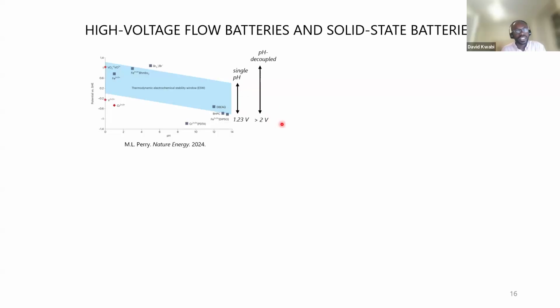But the other advantage we've realized that these membranes carry is that because they are perfectly selective, in this case for sodium ions going from the negative to the positive electrolyte, we can have two different pH environments on either side of the battery. So on one side, we can have an alkaline electrolyte, for example. On another side, we can have something close to neutral. And so this really opens up the space for combinations of electrolytes. We can have a negative and positive electrolyte in a way that we're limited with a conventional polymer membrane, where we have to have a single pH because protons and hydroxides can easily cross over these membranes.